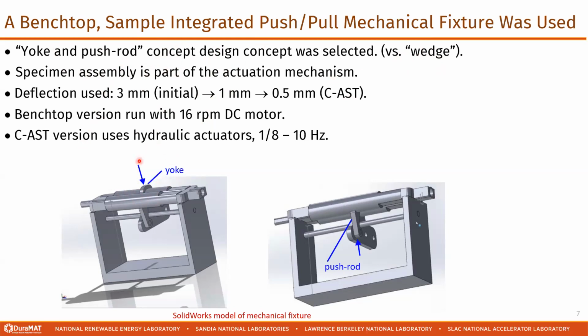If you haven't figured it out yet, the sample assembly is part of the actuation mechanism, right? It's part of the mechanism. We started with a relatively large initial deflection. We were just trying this out. And then we started to dial that back. In later runs, we were at about 1 millimeter instead of 3. And then in CAST, we envisioned dialing this back even a little bit more. This benchtop version is hooked up to a 16 RPM DC motor. It looks a bit like the oil pumps, right? If you're in a petroleum extraction field when it's running. The CAST version instead uses hydraulic actuators, so these are running somewhat slower in practice.